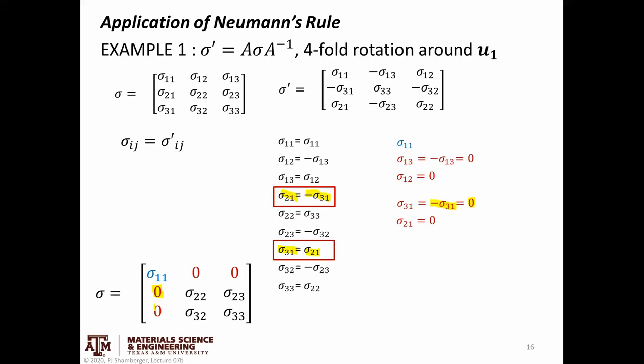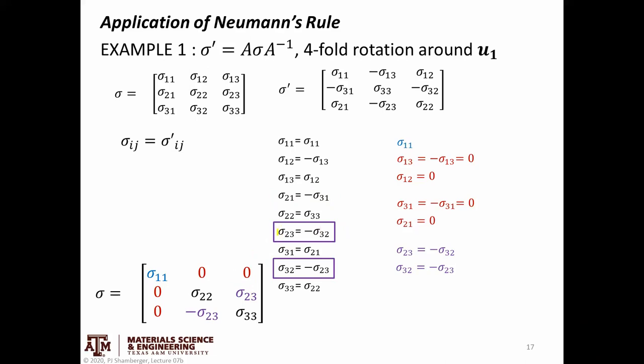The next pair is σ₂₃ equals negative σ₃₂, and σ₃₂ equals negative σ₂₃. If I substitute back in, I get negative σ₃₂ equals negative σ₃₂ — that doesn't tell me anything new. However, I know these two elements have to be opposites of each other. So instead of having an independent σ₂₃ and σ₃₂, I can rewrite both in terms of a single parameter: σ₂₃ up here, and negative σ₂₃ for the other element.